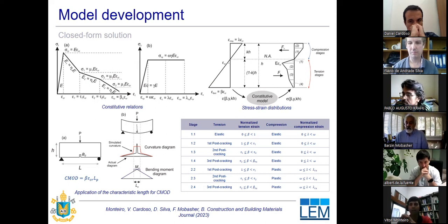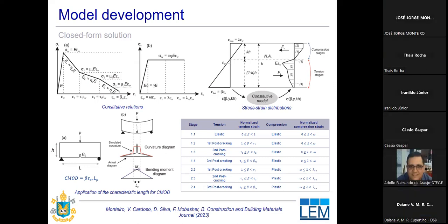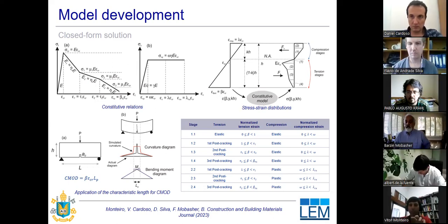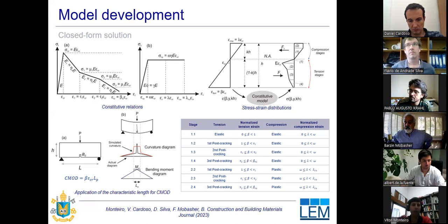We need to know how the CMOD evolves along the fatigue test. So how can we go from the stress strain domain to the stress CMOD domain? This is a key correlation that we need to make to evaluate the CMOD in this kind of test. So we use the characteristic length, which has already been studied by Plizzari, Professor Mobasher, and other authors in the literature. The characteristic length calculates the cracking strain based on these adimensional parameters and is used to transform it into the CMOD. So with the characteristic length, we can go from the stress strain domain to the stress CMOD domain.